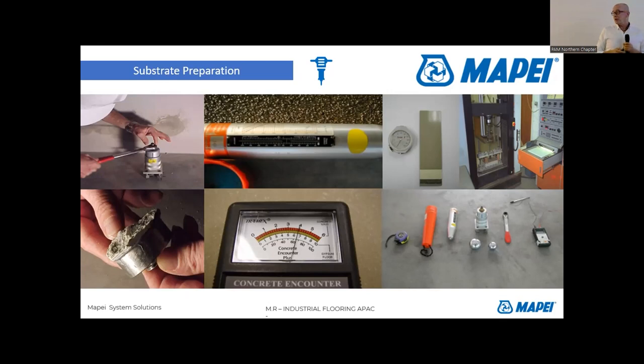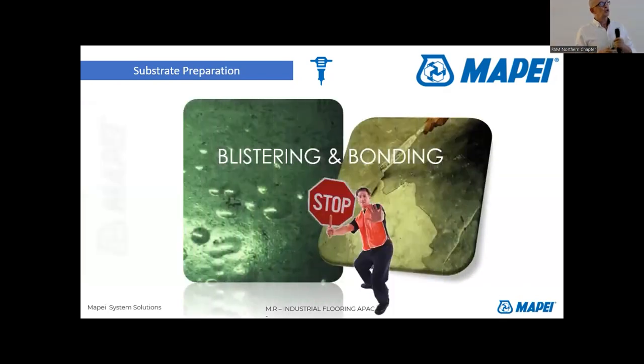Moisture is a big thing, a big thing. So the moisture condition is extremely important before we apply. We have lots of regulations, industry regulations, 3.5% in the concrete, usually around 4, 4.5. We are still good because of the material selection, right? So this kind of instrument, our people on site can use to identify together with the applicator what's going on. Moisture, I mentioned, is a big thing. If moisture concentration is too high, you will get bubbles. It means it needs to be tested. Moisture, as I mentioned just before, needs to be tested.